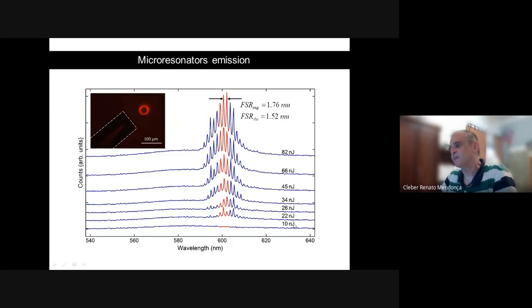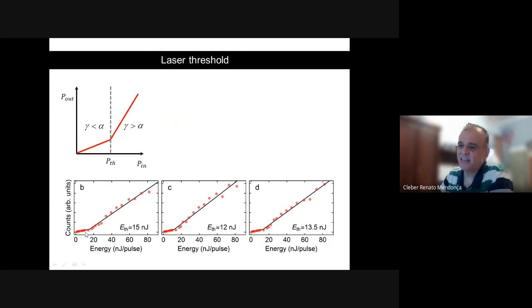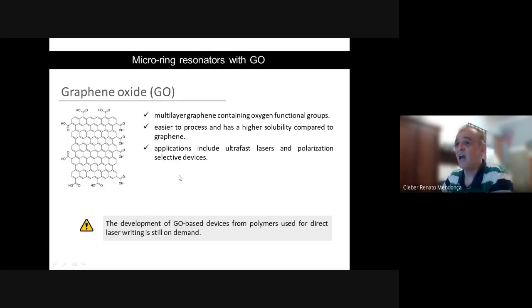Each curve here corresponds to a given excitation power. So now I can plot the emission intensity as a function of the excitation intensity, and you get here the profile of the laser. So here is the threshold of the laser. So we can get laser action with very small excitation energies.